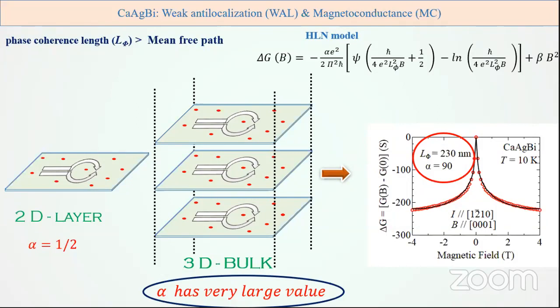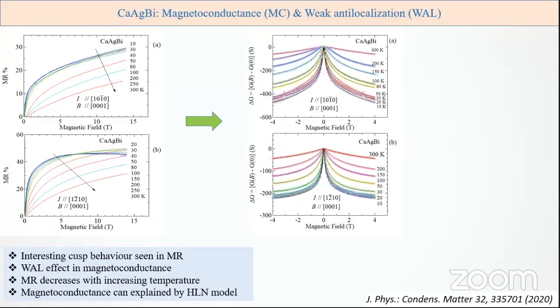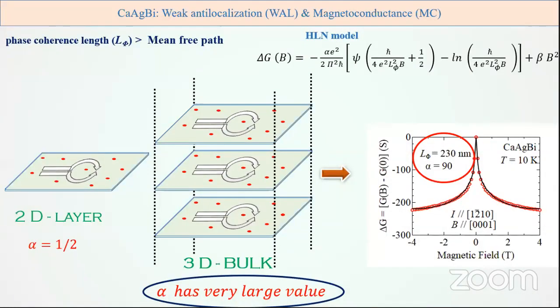No, I would rather say this is coming only from 2D diffusion of the charge carrier in the system, because we tried for a larger field also, 0 to even 14 Tesla at low temperature. We have seen that even without using this beta B square term, it is fitting quite good.